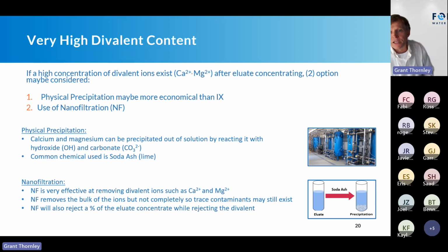Another technology that's actually evolving and getting better is nanofiltration. It's getting better at rejecting the divalents, getting tighter, so a higher percentage of rejection, and getting better at lithium retention, of course, which is the product we want at the highest yield. So therefore, we want to retain as much lithium as possible.